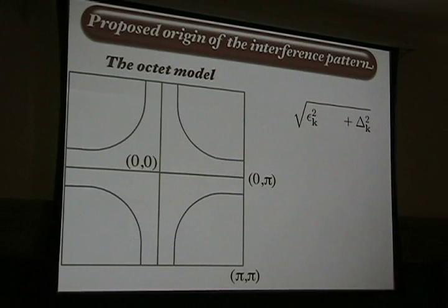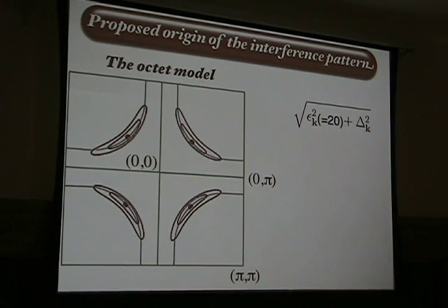And so they proposed, this is a proposition, that the phenomenon is scattering again. Remember, this is a spectrum in the superconducting state, right? It's a Bogoliubov spectrum. So if you look at this as a function of energy, at the Fermi point energy, you just have points. As you go down in energy, you're going down this cone. This is because of the slope of the gap, and this is because of the slope of the dispersion. And so as you increase your energy below the Dirac point, this gets bigger. They call this bananas, which is a fine name for this.